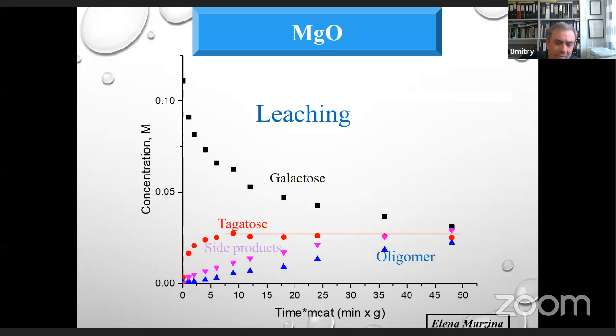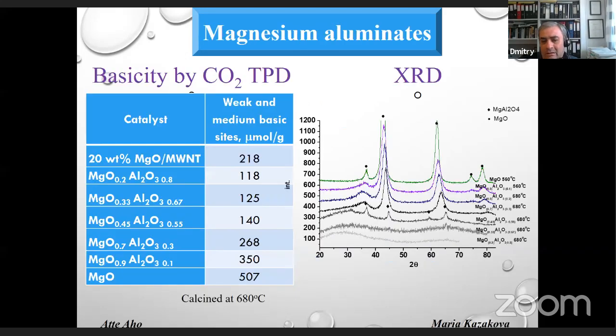Experiments were done using different types of heterogeneous base catalyst, and I mentioned already magnesia as a potentially interesting catalyst. When we started with galactose, we had some sort of transformation of galactose. Tagatose, which is the desired product, was formed, but then we saw a lot of side products. We saw also oligomers. So apparently, in the presence of magnesia, galactose reacted to something else. That's the first thing. And the second, there was a substantial leaching. In fact, the whole amount or charge of catalyst was completely dissolved in the reaction mixture, which is apparently water.